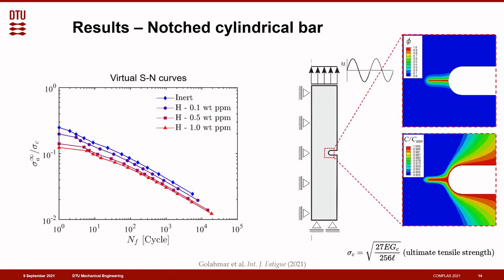So the next case study is a notched cylindrical bar, which is subject to uniaxial tension cyclic loading and exposed to different environments. As you can see in the left figure, virtual S-N curves are obtained for this specific case study. So what we have here is the number of cycles to failure in the horizontal axis and the normalized stress amplitude in the vertical axis. So as you can see, for a given stress amplitude, shorter fatigue lives are observed as the hydrogen content is increased. And in all cases, the number of cycles to failure increases with decreasing stress amplitude, which is basically expected for a typical S-N curve. And here, the slope of the S-N curves appears to be rather insensitive to the hydrogen content.